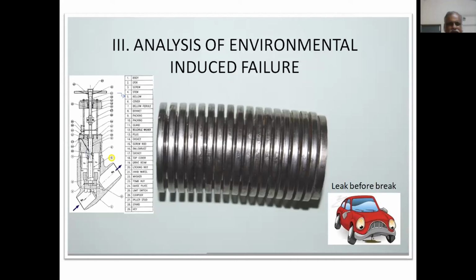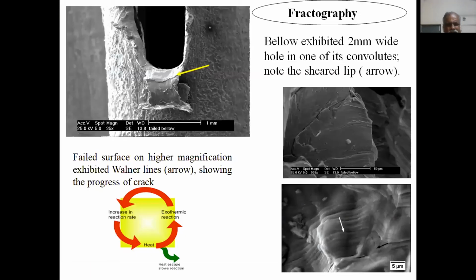In this case, I have given a bellows. A bellows consists of two ply material, two sheets in a folded construction. I could see that it has given way and opened out, with a 3 millimeter or 2 millimeter hole and one lip alone there. There are some interesting discussions. If you look very carefully in detail at this 100x version, it shows some beautiful set of lines on the fracture surface. The same thing further magnified, you could see beautiful striations in addition to a twin here.